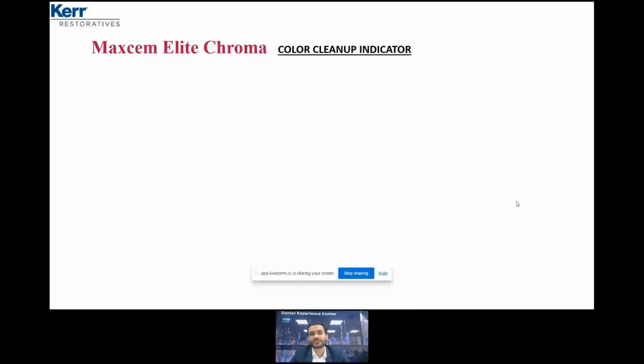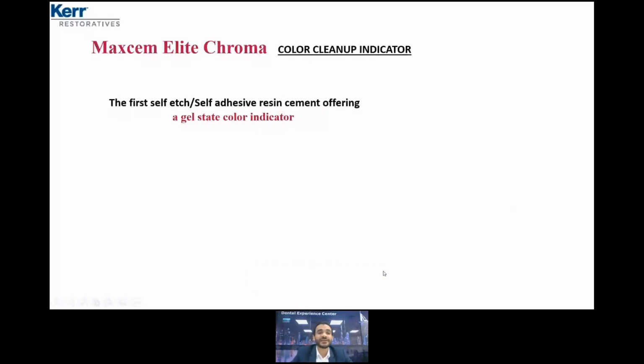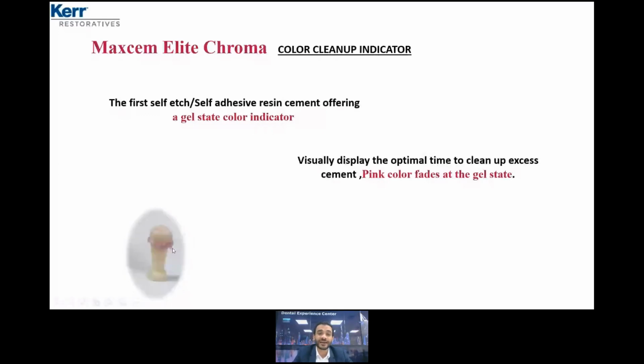Again, we mentioned that we need to remove the excess cement only in the gel phase, in order to be safe and avoid complications or problems. Is it right? Yes. To reach the gel phase, you can use the light cure, which is the traditional way. But in Maxcem Elite Chroma, we developed a gel state color indicator. At the time of mixing and application, you can see the color of Maxcem Elite Chroma is pink. Once the color starts to fade and disappear, you are in the gel phase, which means it is the safe and right time to remove the excess.